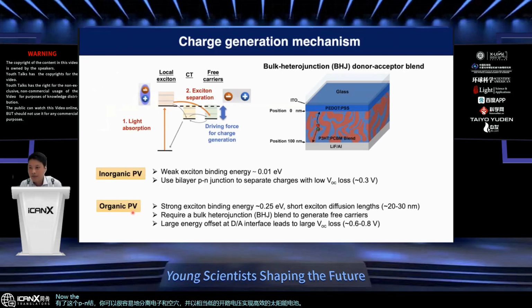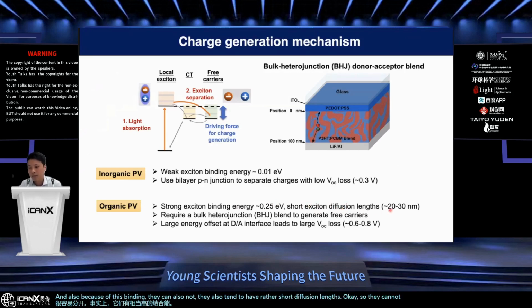Now, the organic material is very different. Due to the low dielectric screening and strong vibronic coupling, the electron hole pairs cannot separate readily, right? In fact, they have rather high binding energies. And also, because of this binding, they tend to have rather short diffusion lengths. Okay, so they cannot travel more than a few tens of nanometers before they release their energy and go back to the ground state, and that leads to energy loss.